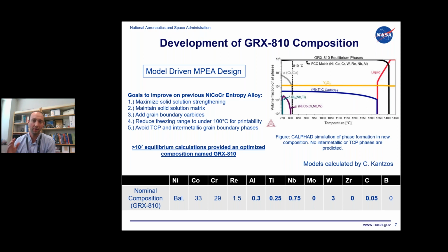So we wanted to take that foundational nickel, cobalt, chrome composition and alloy it to maximize its high temperature properties. We set some goals for our modeling process: maximize solid solution strengthening while maintaining it from operating temperature to melting temp to room temperature, adding grain boundary carbides for strength, all while maintaining printability of the alloy composition.